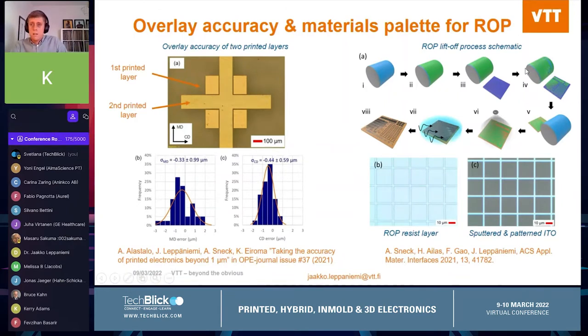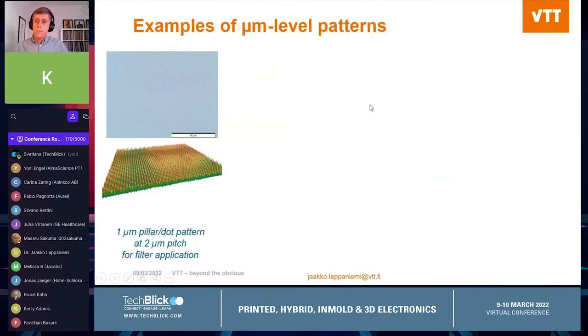In short, we basically print a high-resolution polymer pattern on a substrate with sharp sidewalls, and this allows the patterning of evaporated or sputtered films at micron level resolution. The materials include metals like aluminum, gold, copper, and oxides like ITO. Down here in this right-hand corner, you can see sputtered ITO patterned at few micron resolution. The applications for ROP range from transparent metal mesh conductors to displays, memories, biosensors, and millimeter wave applications.